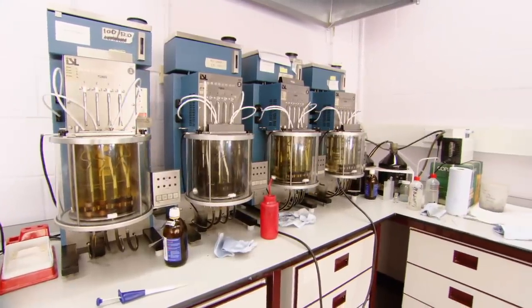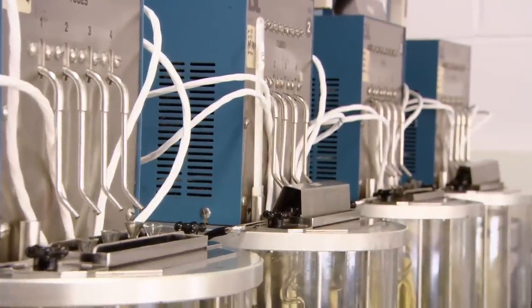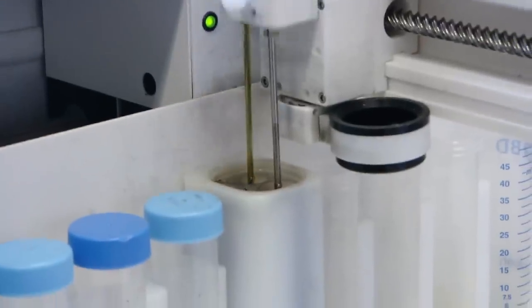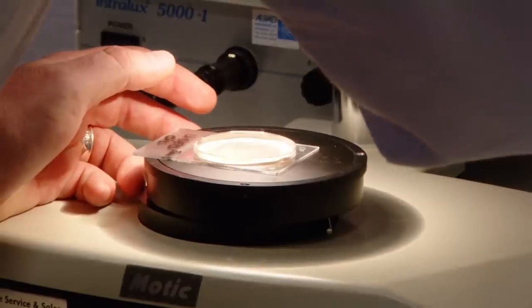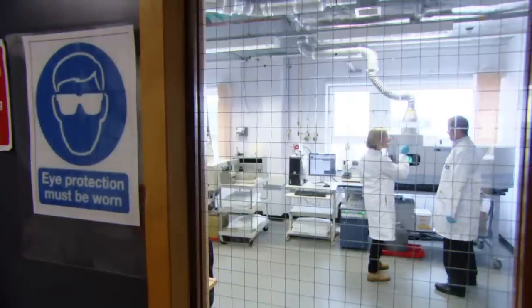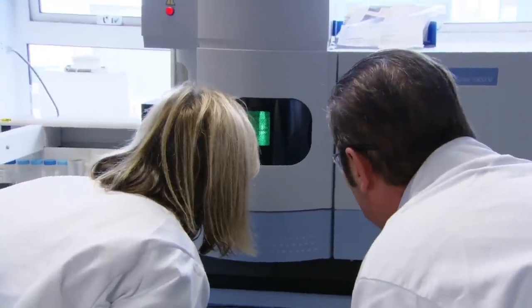Part of that drop is due to fuel seeping into the combustion chamber and thinning the oil — our oil is actually 2.5% petrol. There are solid contaminants too. Over time, microscopic metal fragments break from the engine and are contained within the oil. To find out what our sample contains, Rob uses inductively coupled plasma atomic emission spectroscopy.